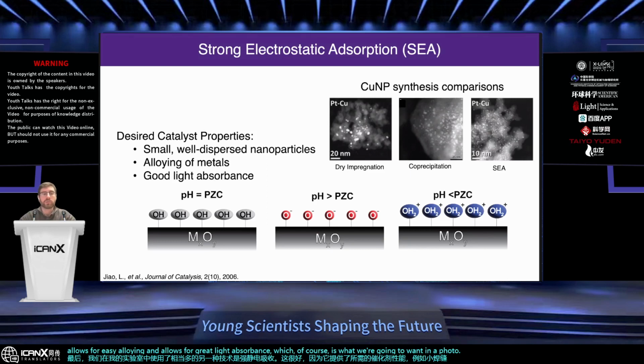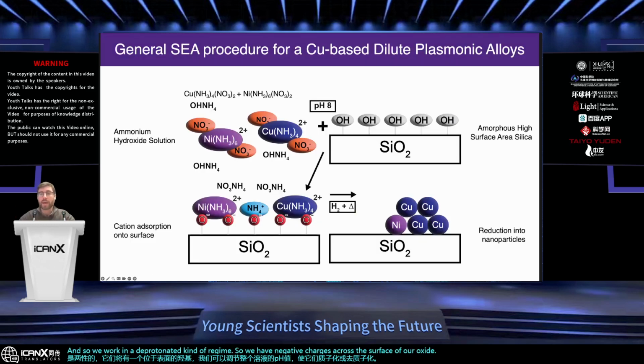So here what we see is that most metal oxides are amphoteric. They're going to have a hydroxide group sitting on the surface, and we can adjust the pH of the overall solution to either protonate or deprotonate those. We work in a deprotonated regime, so we have negative charges across the surface of our oxide. Then we introduce metal cations in low concentrations, and they will adsorb as mixed metals onto the surface of whatever support we're interested in.